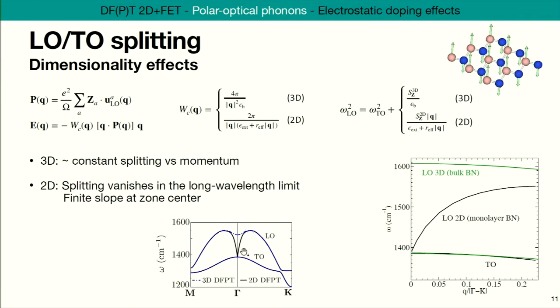So this kind of anomaly in the dispersion is very, very specific, and you don't see those very often in phonon dispersions in general. And this discontinuity you cannot get with periodic image interactions. So you have to be in a truly 2D framework if you want to get this. And here, the dashed lines represent what you get without the cutoff. Even if you put a lot of vacuum, you're always going to get something a little different here in the long wavelength limit, in the asymptotic limit.